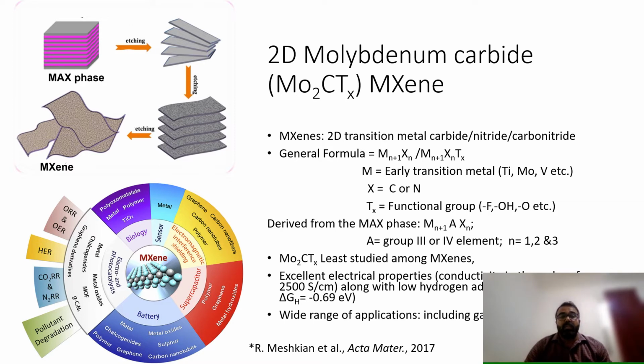One of the reasons for choosing molybdenum carbide MXenes as my research topic is that it is one of the least studied MXenes among the MXene group, because they possess excellent electrical properties. Their electrical conductivity is in the order of 2500 Siemens per centimeter, and they also possess a low hydrogen adsorption energy, in the order of minus 0.69 electron volts, which makes them suitable for gas sensing as well as hydrogen evolution activity. Also, they find a lot of applications in all other fields of science.